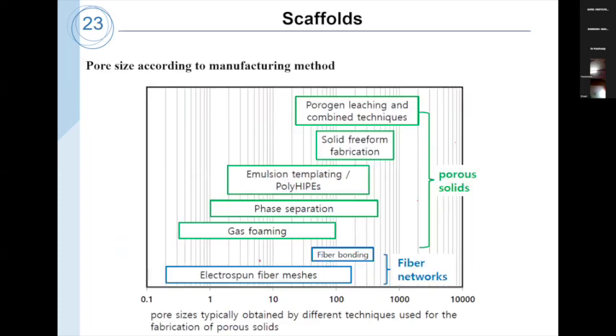So based on pore size, we need to select the manufacturing method. If you see here, there are different types of manufacturing methods to prepare porous scaffolds as well as fiber network scaffolds. For porous scaffolds, we have many choices like porogen leaching and combined techniques, solid free form fabrication techniques, emulsion templating, and phase separation and gas foaming. Each method can produce different optimal pore sizes. You can see here porogen leaching and combined techniques can produce scaffolds with approximately 50 to 1000 micrometer pore size. Solid free form is approximately 100 to 600. Depending on the type of manufacturing method, we can produce different optimal pore sizes of scaffolds.